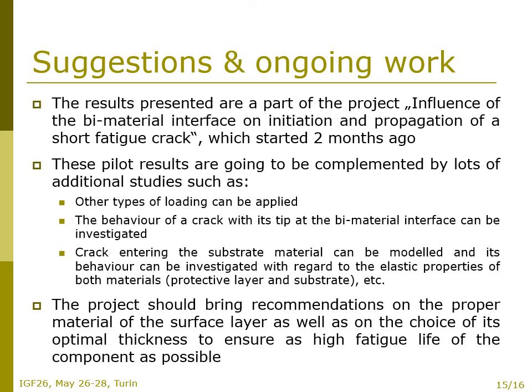At the end of the presentation, the following suggestions on the future work can be made. The results presented are a part of the project Influence of the Bimaterial Interface on Initiation and Propagation of a Short Fatigue Crack, which started 2 months ago. These pilot results are going to be complemented by lots of additional studies, such as other types of loading can be applied, or the behavior of a crack with its tip directly at the bimaterial interface can be investigated. Crack entering the substrate material can be modeled, and its behavior can be investigated with regard to the elastic properties of both materials, protective layer and substrate, and so on.